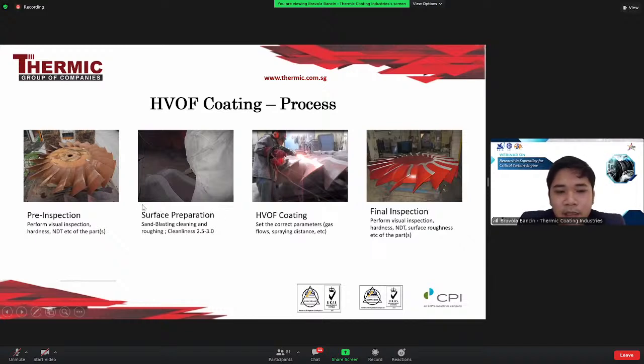And then we do surface preparation. The surface preparation is very mandatory. We use sandblasting with aluminum oxide, for cleaning and roughening the surface. The minimum requirement for cleanliness is 2.5 to 3 cleanliness level. It means no dust, no contaminants, and ready to be coated. And then the process of HVOF coating: set the correct parameters like gas flow, spraying distance, etc., depending on the powder that will be coated onto the blade or the parts, and then final inspection.